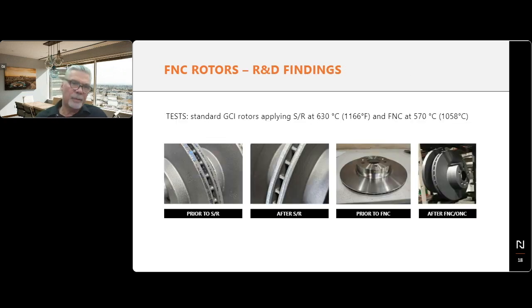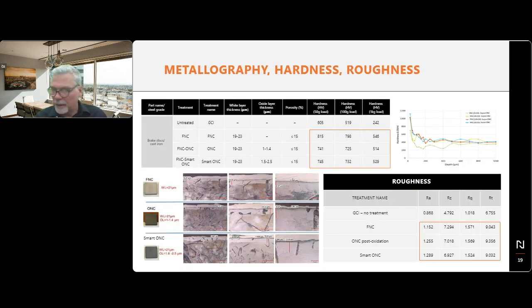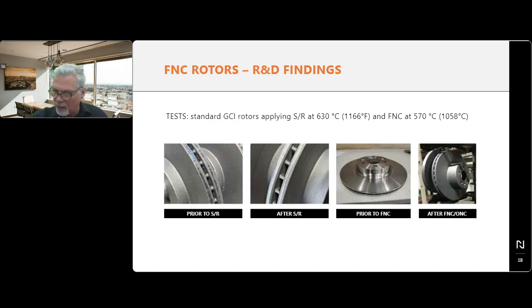So we did many tests. The test we have done is different stress relief operations done at approximately 630 degrees Celsius or 1166 Fahrenheit. And we did nitrocarburizing at 570 degrees Celsius, which is 1058 degrees Fahrenheit. Sorry for that typo. And we followed those trials by a series of tests to see how the discs will behave.